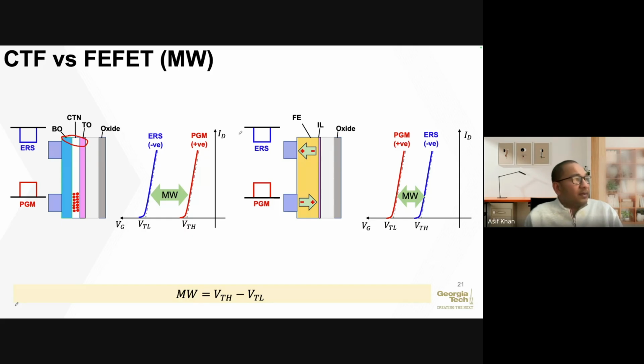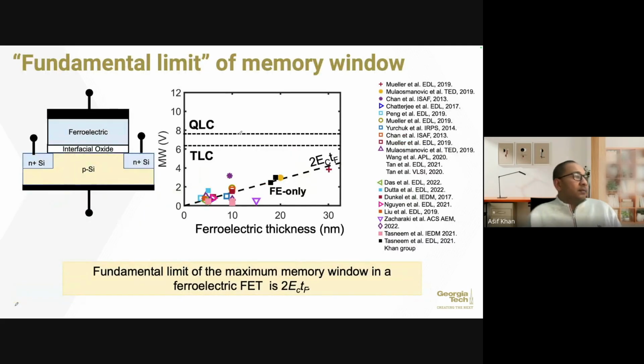All right. So with that basics, let's go on and see how a ferroelectric field effect transistor performs and whether we can get to those metrics that we mentioned earlier. One of the things at the get-go of our project was that there is a notion of a fundamental limit of memory window. One of the key metrics that we need to achieve for ferroelectric NAND technology is what we call the memory window, the difference between the two threshold voltages for the two different directions of the polarization. And the value that we needed was above 6.5 volts.